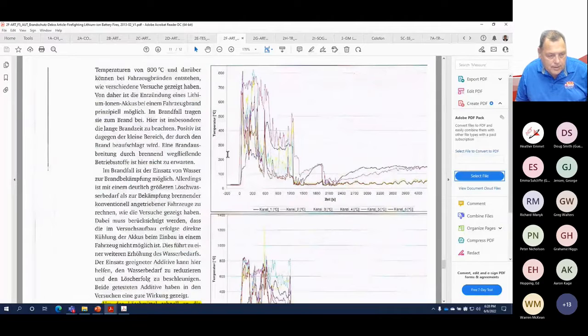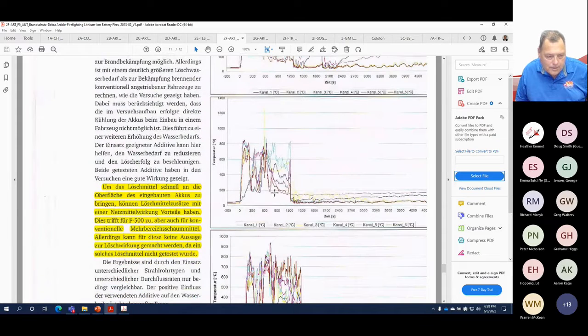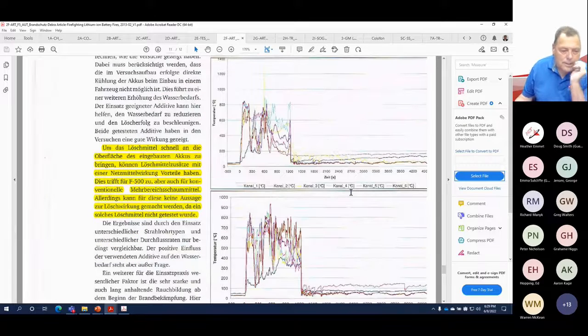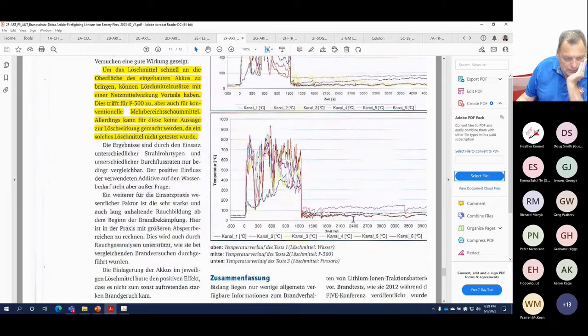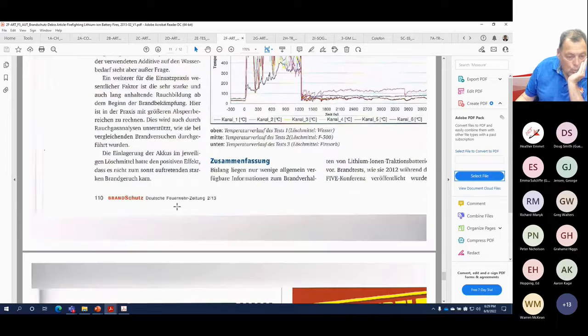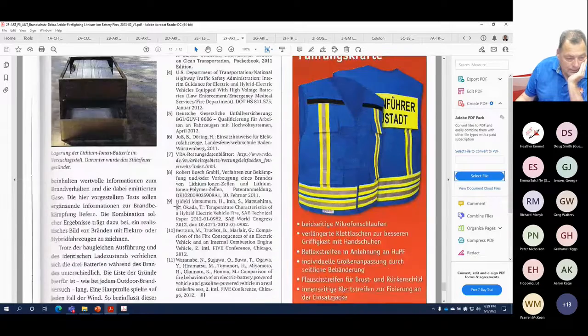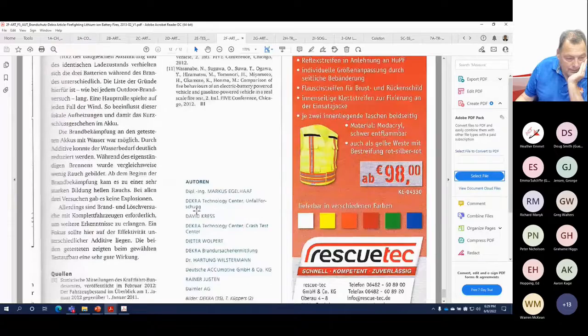Some of the things you see here is the temperature reductions, and you can see like a plain water takes time for the temperature to go down, and then you see it starts to come back up as soon as you stop the nozzle. One of the big differences here with the F500, temperature straight down and remains down. And we have some other tests that's showing that, and we can explain why this agent does that.